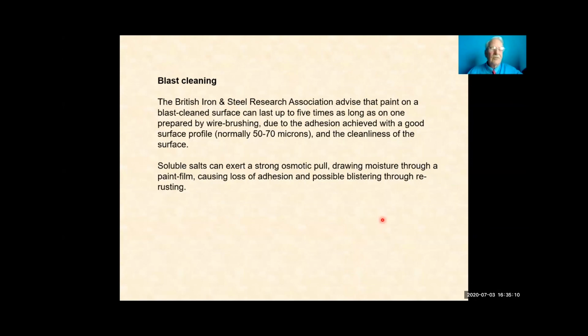You'll find the industry very widely uses blast cleaning, and that's partly because the British Iron and Steel Research Association in Britain advised that paint on a blast cleaned surface can last up to 5 times as long as one prepared by wire brushing. And that's because it is rough, unlike a wire brush surface. It gives a lovely, good surface profile, ideally 50 to 70 microns. And the surface is very clean if you use blast cleaning.